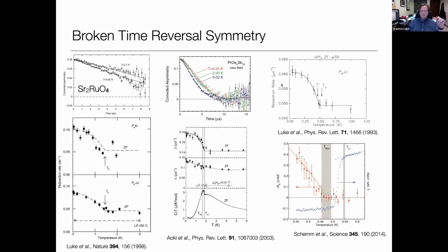This has been seen in a number of superconductors. We've seen it ourselves in the case of uranium platinum 3, which is a heavy fermion superconductor. Other groups have seen it in, for example, these clathrates like praseodymium osmium 4 antimony 12. And it's not just seen with muons. There are now experiments using Kerr rotation, a group out of Aharon Kapitulnik at Stanford, only 20 or so years after us, managed to observe the same thing in uranium platinum 3. So it's not just a muon technique. You can see these broken time reversal symmetry states with other techniques as well.